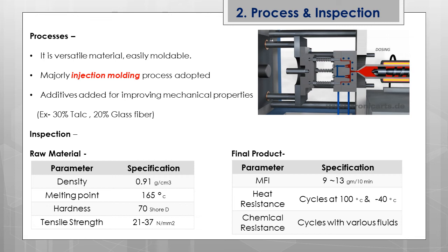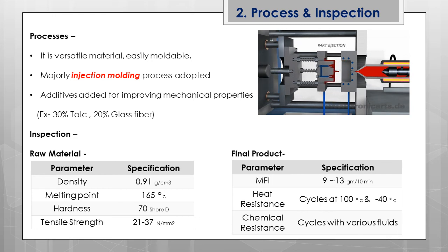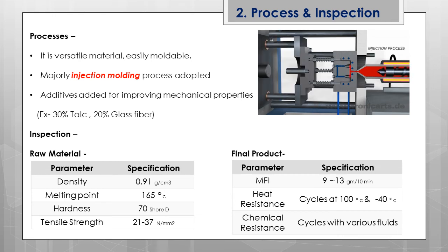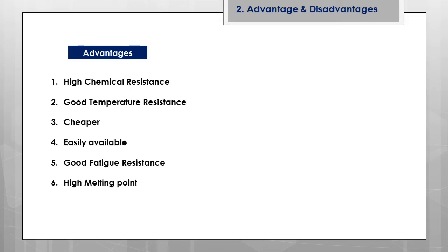For chemical resistance inspection, the product is exposed to different chemicals ranging from water to brake oil, diesel, and food chemicals for a certain duration. After exposure, surface conditions and degradability are evaluated before the final product is approved. These are the standard inspections followed for PP raw materials and final products.